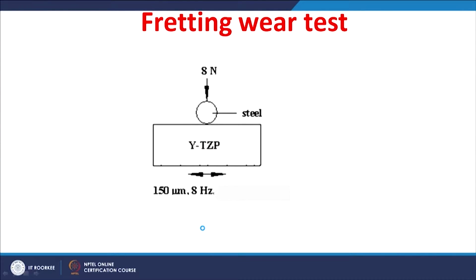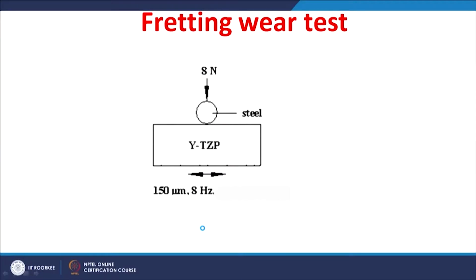So, with this information on the material, the fretting wear test was conducted for these zirconia ceramics against a steel ball. Fretting was done in mode 1 fretting conditions, which gave the gross slip conditions at the contact.